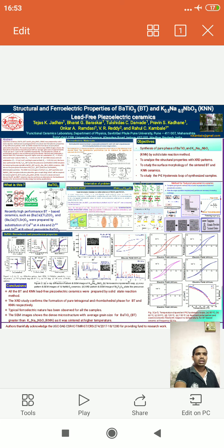We can see a d33 versus texturing degree plot. After texturing, the random polycrystalline material becomes like a single crystalline material. This is a cost effective technique useful to enhance the piezoelectric and ferroelectric properties of the material, in which templates are used to grow the grains of the polycrystalline material. Templates are particles in which the crystal axis is aligned in a particular direction.